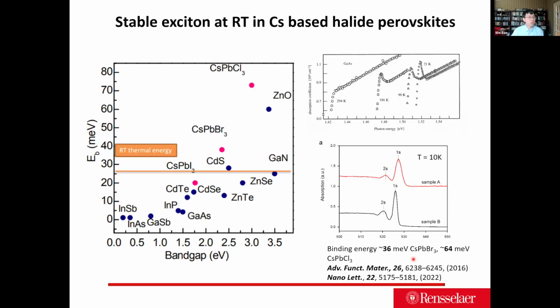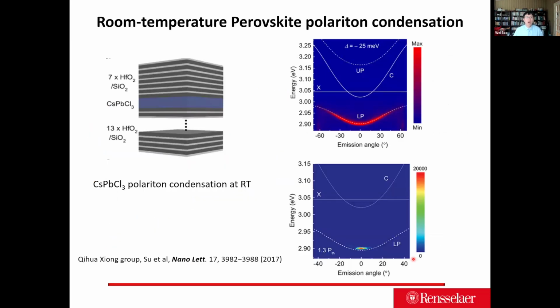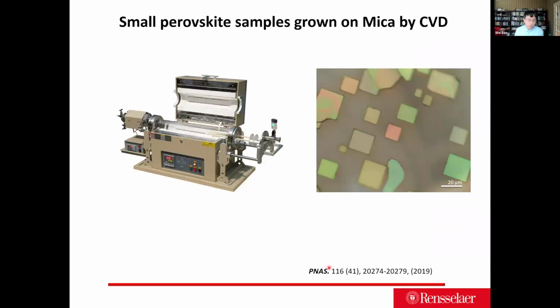So this is a great material, solution processed without bothering any MBE growth. The first trial in the field came from Professor Qihua Xiong's group and his PhD student Rui Su. Essentially, they integrated cesium lead chloride together with hafnium oxide and silicon dioxide in a DBR cavity, and at room temperature they could already see polariton condensation. This was back in 2017. In one of the follow-up works we did with Rydberg exciton-polaritons, we also saw that they can reach strong coupling, even using a CVD sample.